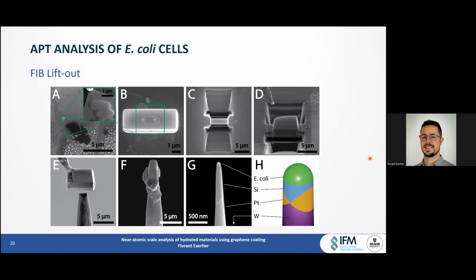And I have to admit that gauging the presence of the sample in the Z direction during the annular milling was quite challenging. But there was a big difference between this sample in particular and others, where either I missed the sample completely and got pure platinum, or I removed too much and hit the silicon or the tungsten directly. To me, it seems pretty convincing that in this case we were right in the cell, and that's also confirmed by the sort of entanglement, I don't think this is the right word, of the water and the cell. I'm not sure whether any other type of material would be entangled in such a way in the results.